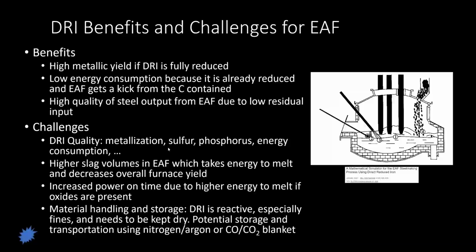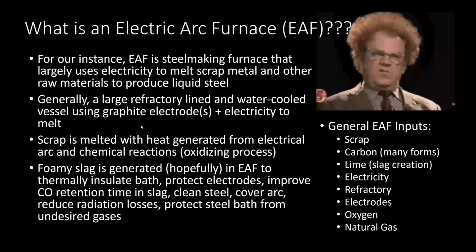In the end, how long does it take for me to melt it? What is the effect on my slag? How much energy does it take to melt it? Once again, higher slag volumes - if you have to add lime in order to counterbalance, you have that. Increased power-on time, and then material handling is always a concern if you have DRI, since it's reactive. So some people have to keep it underneath some type of inert gas environment, nitrogen and argon storage, or some type of CO2 blanket.